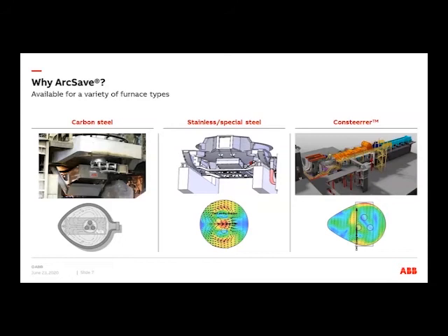So, in which furnaces can we use the ArcSave technology? On the left side, you see a normal conventional bucket-charging carbon steel furnace with an EBT tapping system. We can use it for the stainless special steel manufacturer, which normally uses a spout tapping furnace with a higher angle during tapping. We can also use it for the latest flat bath operation technology, for example the Consteel furnace. In this case, we are shifting the stirrer 90 degrees, perpendicular to the normal direction, towards the Consteel charging area.